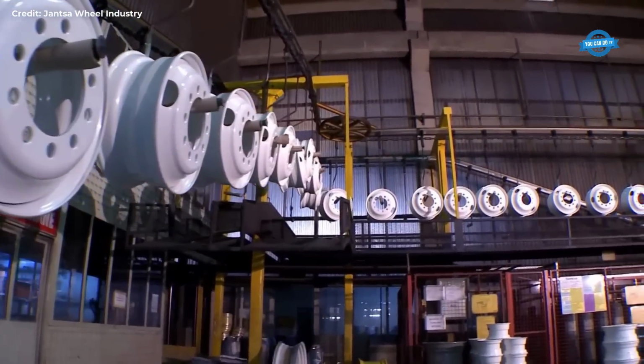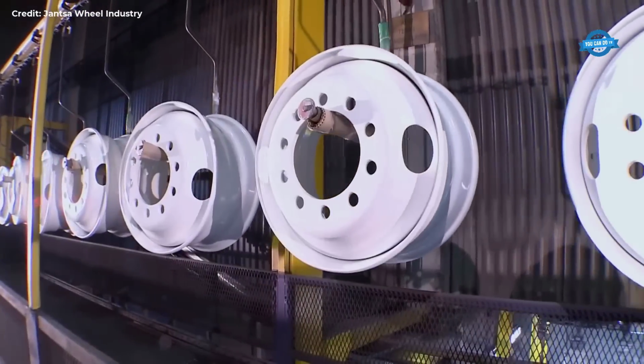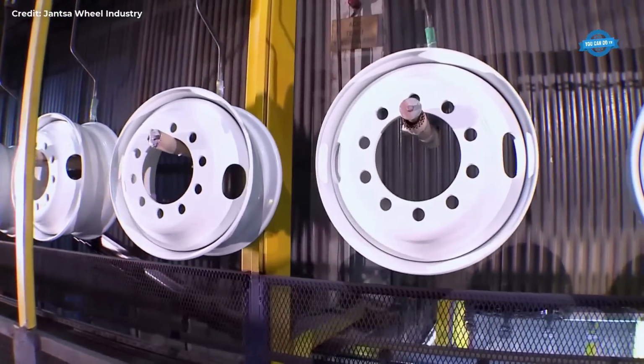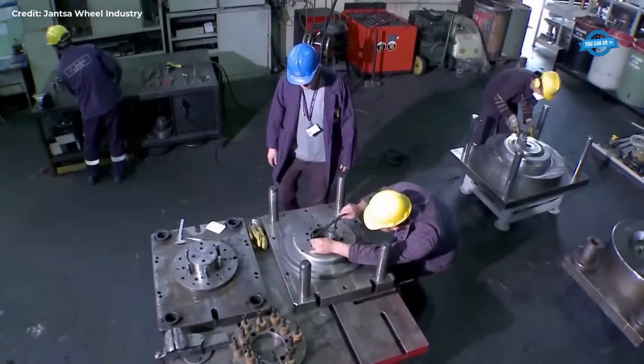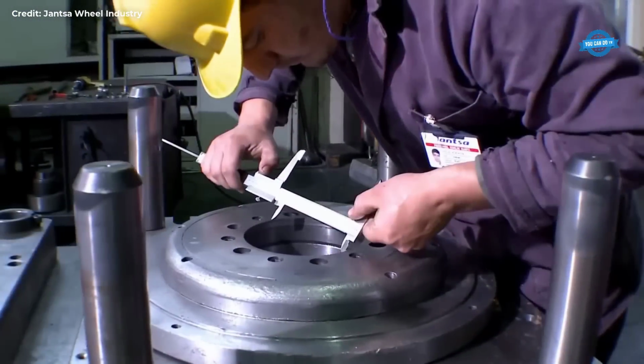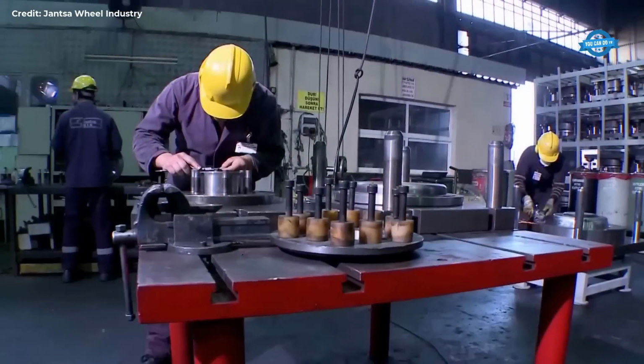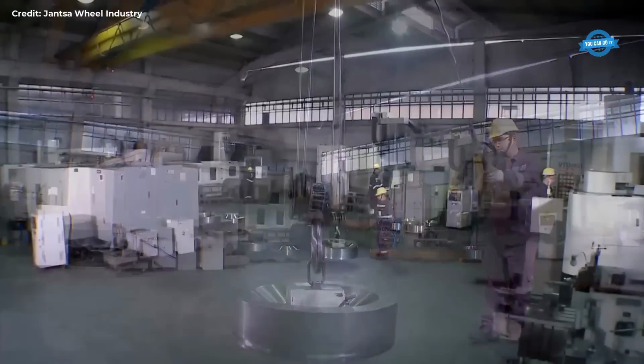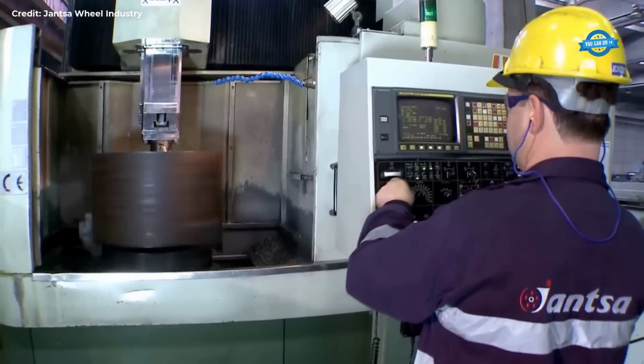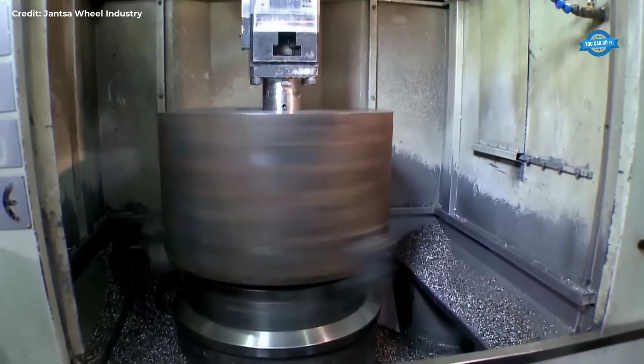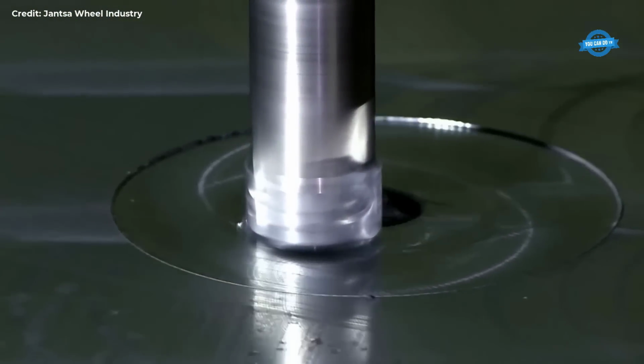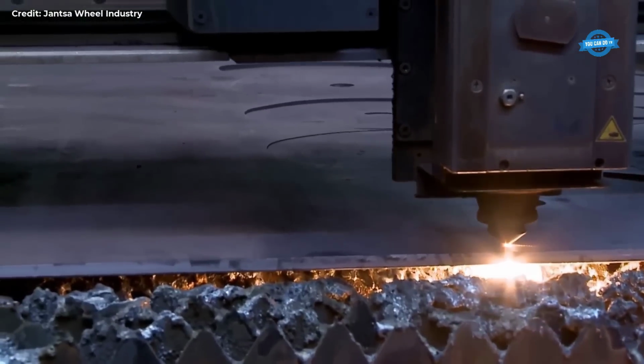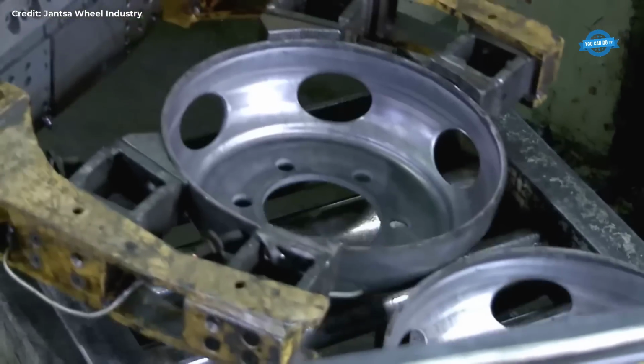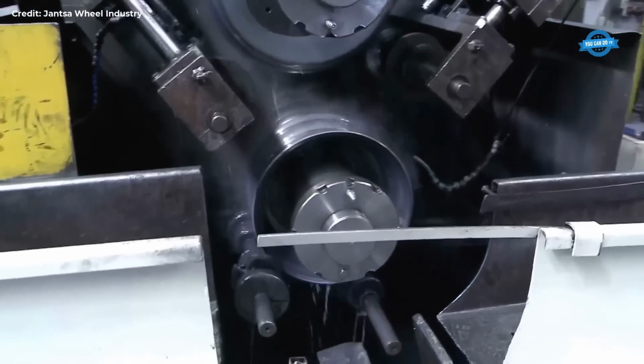Surface treatment is paramount for longevity and corrosion resistance. Shot blasting maximizes rust resistance, followed by automotive standard double anti-corrosion protection through zinc phosphate pre-treatment and epoxy E-coat. Cathodic dipping safeguards hard-to-reach areas, with lead-free paint minimizing environmental impact. These wheels boast salt spray rust resistance of up to 1,000 hours and offer over 200 paint options, meeting stringent requirements across heavy equipment categories.